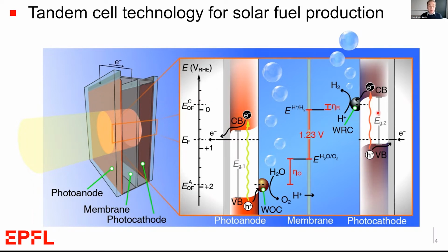And both of these semiconductors then will combine the photopotentials sufficient to overcome that 1.23 volts, which is necessary to split the water thermodynamically, and also the overpotentials for the water oxidation reaction on the photoanode and the water reduction reaction on the photocathode. Now, a key point here is the interaction between the semiconductor interface and the water, where ideally we would form this Schottky type junction that can help drive our photogenerated holes in the photoanode and our photogenerated electrons in the photocathode towards that interface, where they can react on a water reduction catalytic site on the photocathode or a water oxidation catalytic site on the photoanode. So this is the concept of the photoelectrochemical approach, and then the analogous system with the photocatalytic particle-based system can also be imagined.